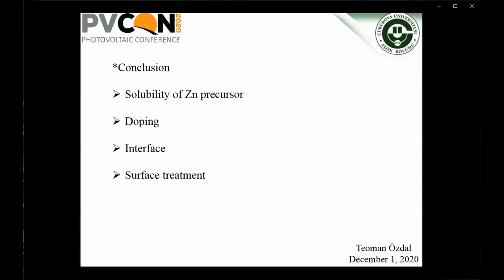In conclusion, we first say that the solubility of zinc precursor in the solvent is the key factor of zinc oxide crystallinity. And the nitrogen doping has another good effect on the device efficiency. Our future work will be focused on the interface. We are planning to apply surface treatment on zinc oxide layer and add extra intrinsic layer between zinc oxide and cuprous oxide.